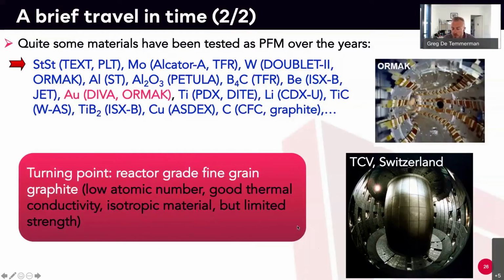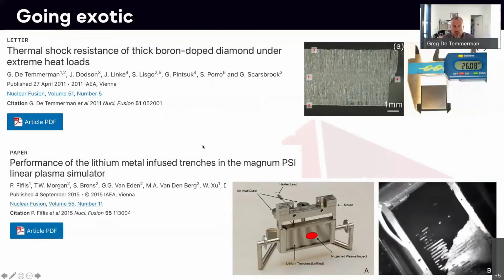People even looked at CFC, carbon fiber composite, because it has better strength, and you can engineer the fibers to increase the thermal conductivity. Some people went even more exotic. I led a project at some point to look at diamond. Why diamond? Well, if you like carbon, graphite is great, but diamond has the best thermal conductivity of all known materials. Of course, it doesn't come cheap. But we had a project with a company to produce thick artificial diamond, which was doped with boron, and we tried that, and it has a world record in terms of thermal shock resistance of any material ever tested. So it was pretty good, but it's too complicated to make, you don't get the throughput, and it's also a bit sensitive to neutrons.